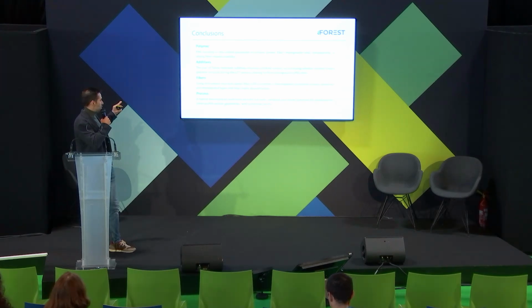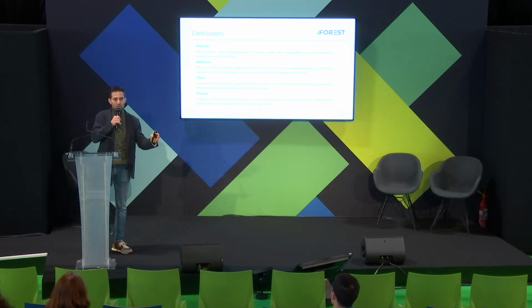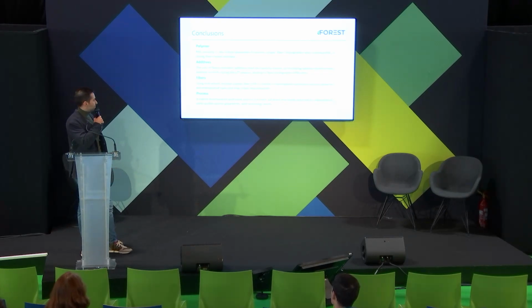And regarding the process, a hybrid thermoplastic pultrusion process has been validated, which is great. Probably the profile that we're using, a flat profile, is not the most appropriate for a pultruded profile, because you're looking for different geometries. But it has been validated. We have demonstrated the technology, and we know that selecting other profile section geometries might have promising results using this technology.